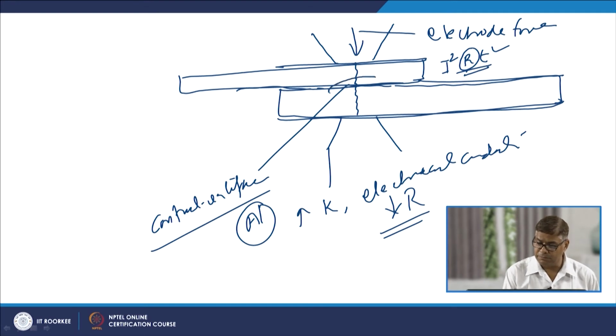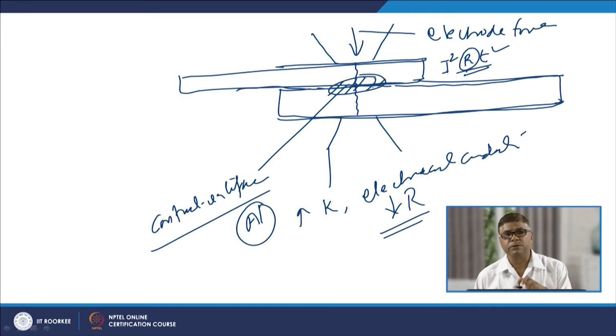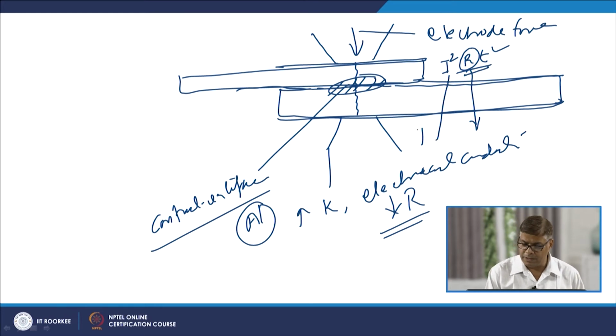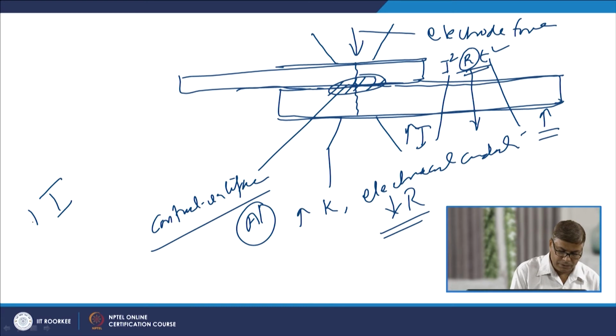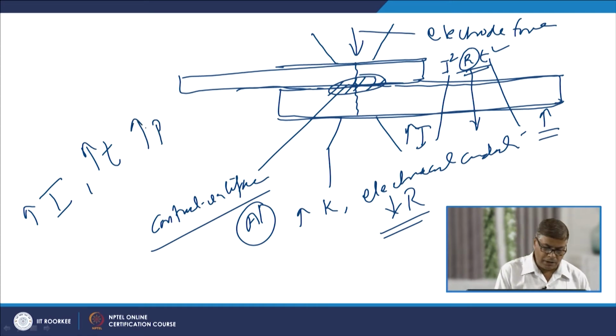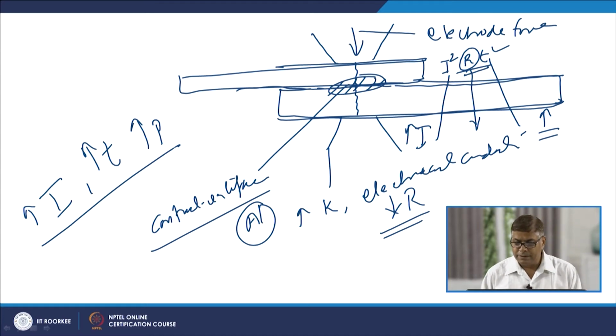Therefore, in order to generate a sufficient amount of heat at the interface, so that the softening and the required partial melting to form the nugget can take place, we need to counter the reduction in the value of R by increasing the current and the weld time, the time for which welding will be taking place. So, in general, the welding current, the time for which current is allowed to flow, and the electrode pressure used to hold the sheets together are all increased, so that the required amount of heat for softening as well as partial melting can be facilitated.